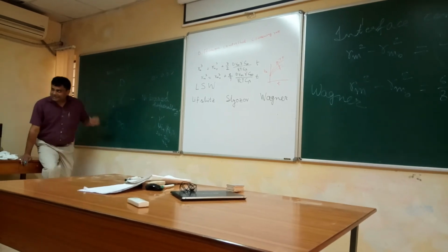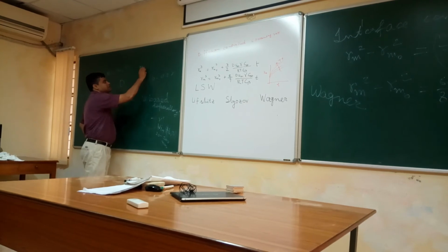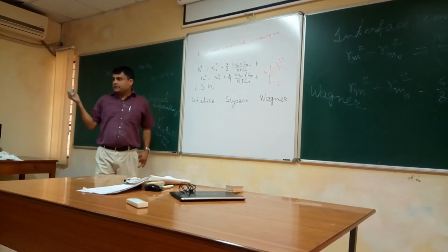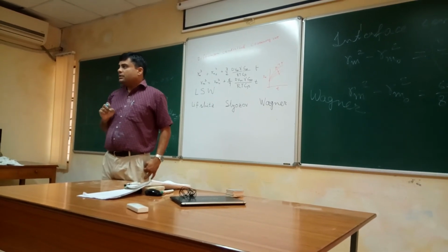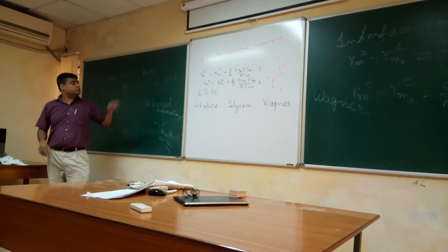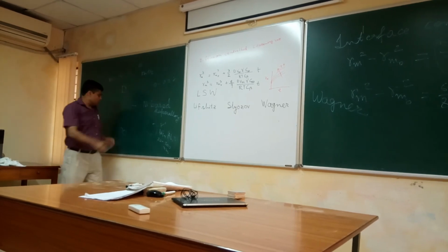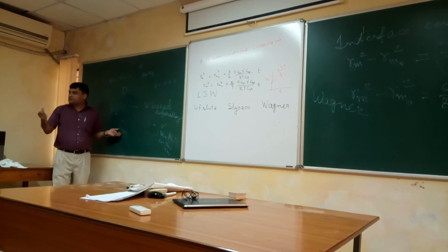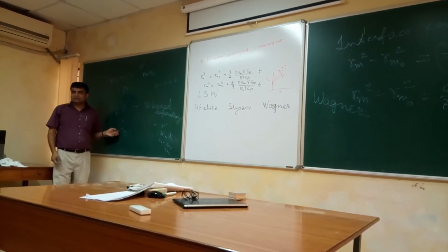For example, in tungsten, thoria particles are used. Tungsten filament, this bulk filament, small thoria particles are used. At that high temperature, because there is no solubility of thoria in tungsten, the C infinity of either thorium or oxygen is almost zero.